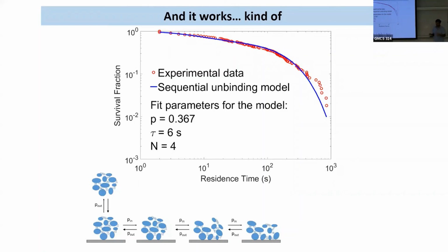Okay, so this is for the computational guys. There are 2 ways you can count. You look at a protein that comes, sits on the surface and goes off, and you're recording this video, so you look at frames. Frame 1, protein came. Frame 2, it's there. Went off. Oh, came back. That means it was blinking, so you have to connect those dots. If it's in exactly the same spot, then it never actually went off. It was just blinking on and off, because these are fluorescent proteins, so they don't stay bright all the time. So you correct for those things and connect those trajectories.